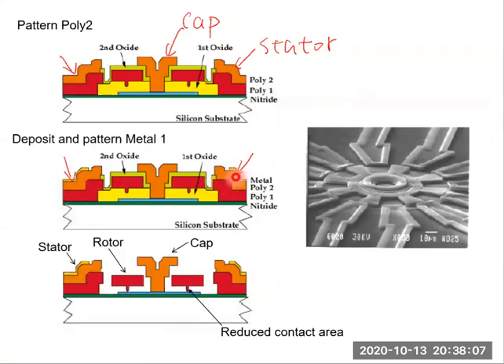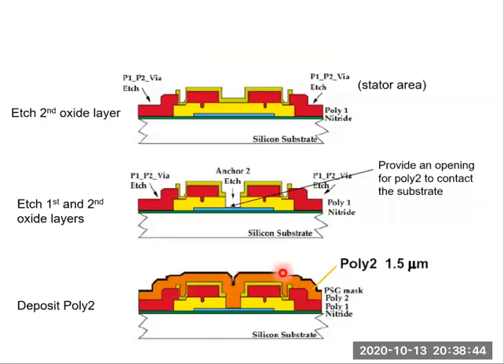Note that this metal layer needs to form a good electrical contact with the stators. So you need to form good ohmic contact with the poly 2. In solid state physics or semiconductor physics, you probably have learned that in order to form good electrical contact, we need to have an ohmic contact. Or in other words, poly 2 needs to be heavily doped. That's the reason we need to coat a PSG layer above poly 2 to heavily dope this polysilicon layer.